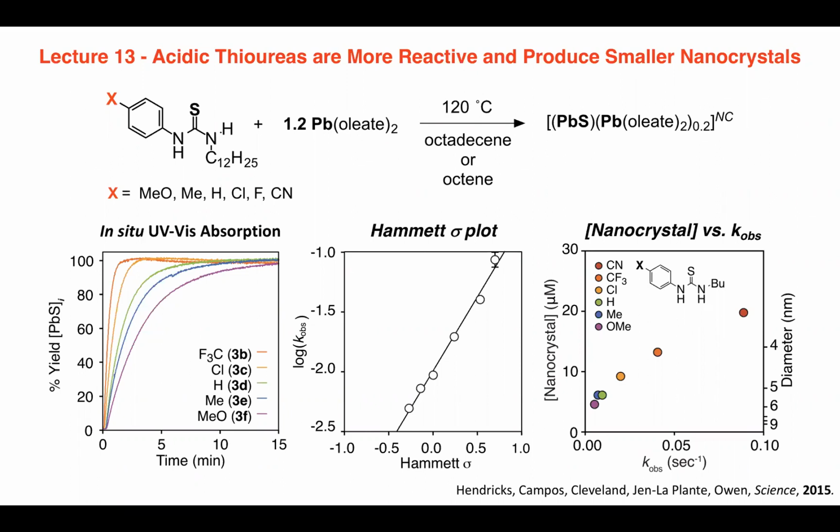You can also say all of these compounds likely break down by the same type of mechanism because there's a systematic change in the reactivity with the substituent pattern according to this Hammett relationship. So they're behaving themselves, is another way to say it. So the reactivity, these curves, all dictated by the breakdown of this compound. And then, of course, the thing we mentioned was the rate of that breakdown turns out to be related to how many crystals nucleate.